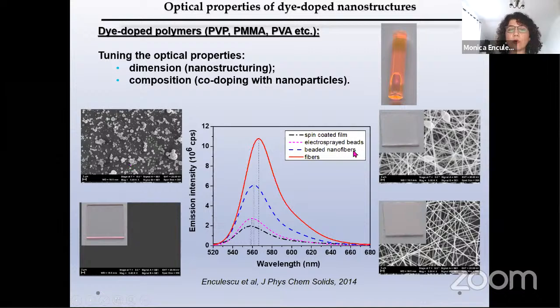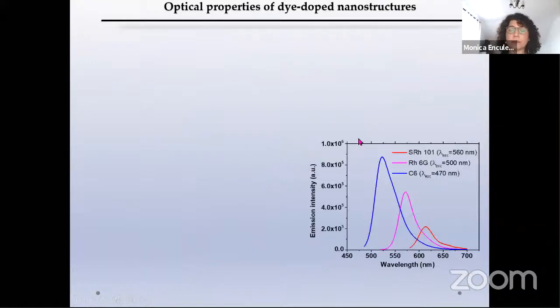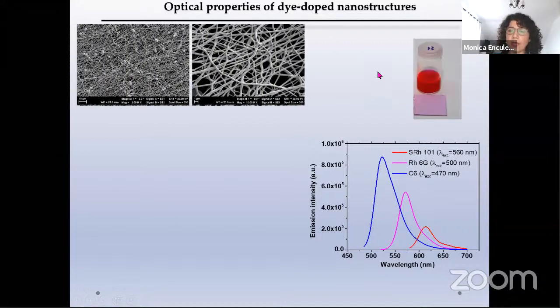So for each of these morphologies, we have a different emission of this type of structures. So with the same solution, we can obtain different emission wavelengths for our structures. And of course, different emissions can be obtained by doping with different materials, of course. But at the same concentration of the dopant in the solution, we obtain, of course, the mat of fibers.